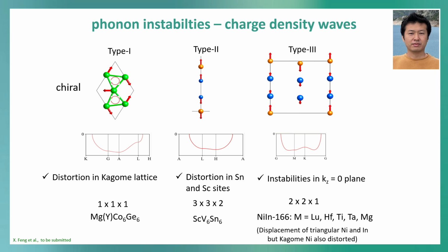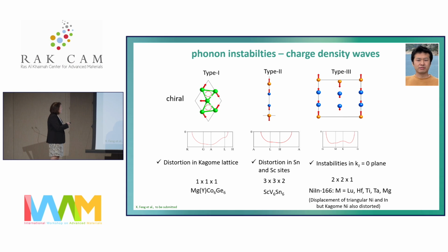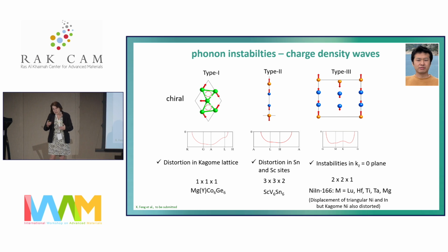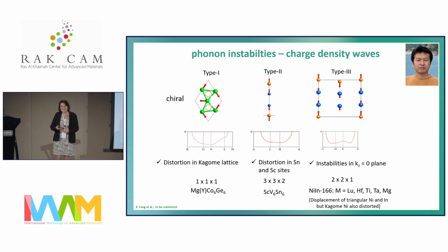One is very interesting because I like chirality. For other purposes, like catalysis, for example, you can make these materials which have a chiral charge density wave if they have the minimum here at the A point, and then you can have the charge density wave which you already saw in scandium vanadium tin, and you can have a third type of charge density wave. So many of the materials are not yet investigated. Unfortunately, Subhajit also got a job in India at NISER, so after 3 years and Humboldt, I again have to find somebody. I'm waiting for someone who continues this synthesis.